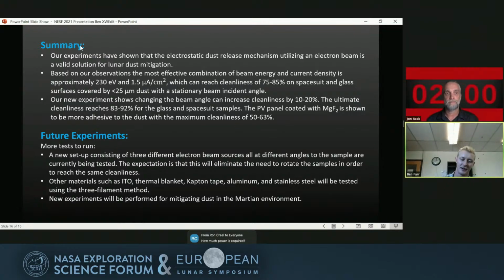Yes, sorry, I was trying to rush through all these slides and I forgot that part. All of our tests, we did them with a JSC-1 lunar simulant that was sifted down, so it was all less than 25 microns. And then to deposit the dust onto the sample, we just sift it straight onto the sample to try and get it as evenly distributed as possible. And as far as determining the initial thickness of the layer, we wrote a program so that we can take a picture of the background, then take a picture of the dust layer, and that'll tell us how thick we're starting out.